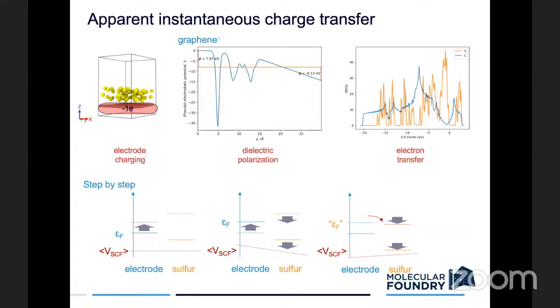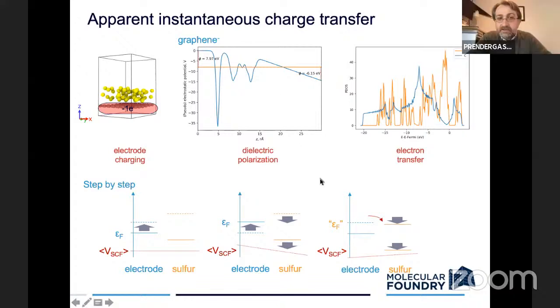So, out of curiosity, I am willing to know how the thickness of the thin film affects the dynamics of the charge transfer, electron transfer you are mentioning. Okay, so in the worst case scenario, if you don't constrain the charge, then the thicker your dielectric, the worse this effect is, and the more likely it would be that your charge will emerge on the surface instantaneously, but that's unphysical.